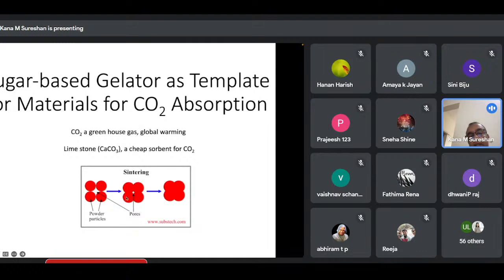But the problem here is that after a few cycles of carbonation and decarbonation, which happen at very high temperature, the porosity of this material becomes much less and it becomes non-porous, an amorphous material. After some time, it cannot take a lot of carbon dioxide. It can take carbon dioxide only at the surface. Most of the inside part will not be accessible, as carbon dioxide cannot go to the inner core, and thereby it will only react at the surface. So this is called sintering. This is bad, actually, because it is killing the efficiency of this carbonation process.